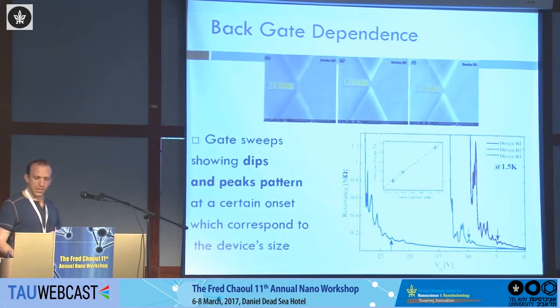We had 3 different devices, 3 different sizes, 100 to 200 nanometers, and we cooled them down in pumped liquid helium to 1.5 Kelvin. What you can see here is the resistance in megaohms versus gate voltage. As I said before, you can change the backgate of the STO, and by that change the energy of, let's say, the electrons, or the carrier density of electrons. And the normal plot will just go monotonically up by depleting electrons. But this is just something different.